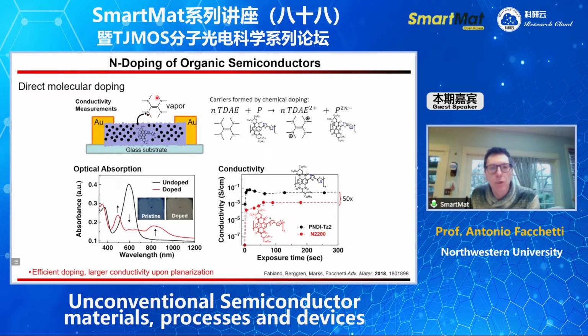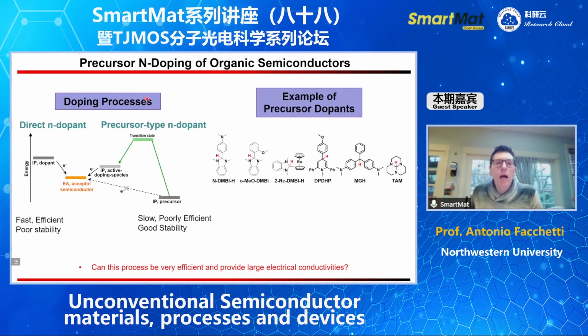An N-type using this amine. This amine can directly transfer electrons from the molecule to the semiconductor. And we have done this for a number of materials. The doping process by direct doping is typically very efficient. However, the result is you start with a molecule where the LUMO level, or electron affinity, is very, very low. So the molecules are not very stable.